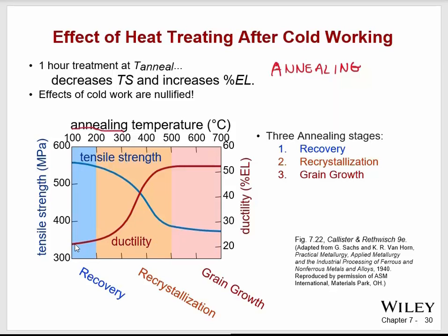So the whole idea is that the recovery period is the process of beginning to release those planes from their locked state. Then once they are no longer locked, more and more of them free up during the increase in ductility phase, which is the recrystallization phase, where the domains that were locked before have a tendency to form new domains, new little regions of crystal. You remember when we were talking about domains, we were talking about different little regions of crystal, right?